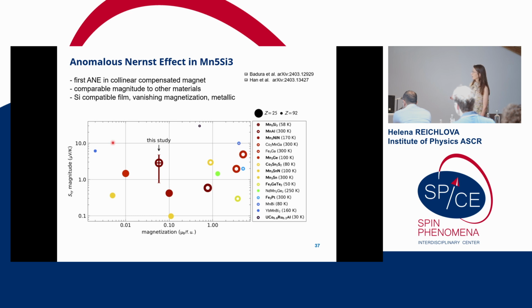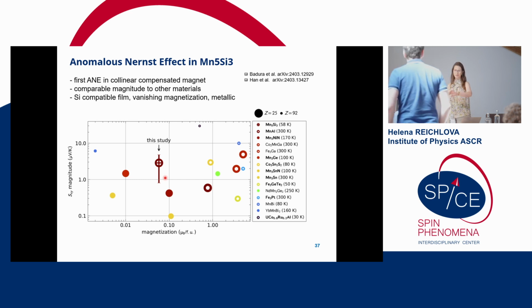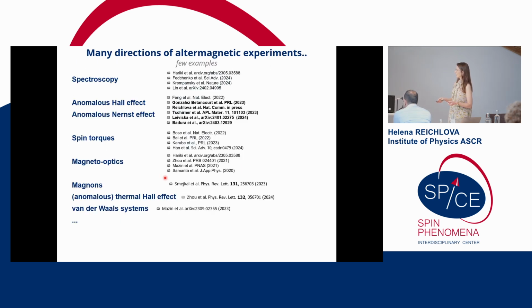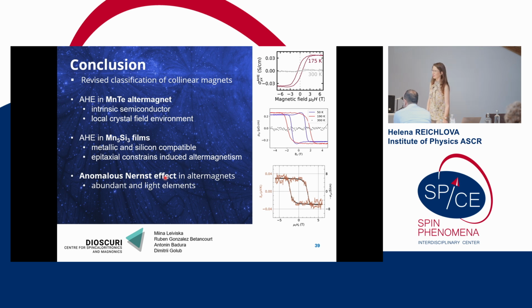Then the ytterbium one, again a very large coefficient, but still a very heavy element. In the next line, we have the Co2MnGa ferromagnetic topological ferromagnet, which relies on the relatively fragile contributions from the intrinsic anomalous Nernst effect. And then we are almost already in our range, where we have our simple Mn5Si3 thin films compatible with silicon. This shows the potential: the first try on these lightweight elements, and we already have a pretty solid anomalous Nernst effect. So this brings me to the conclusion, and I will just leave it here for the questions.